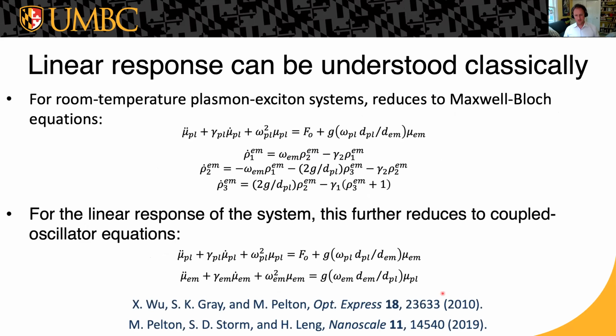And if you're interested only in the linear response of these systems, relatively weak excitation intensity, where the system stays in its ground state, then this reduces further to a fully classical pair of coupled harmonic oscillators, where each oscillator represents the dipole moment of, say, the plasmon and the dipole moment of the exciton. They're coupled together through the near field of the plasmon. And this simple pair of classical coupled harmonic oscillators reproduces quantitatively the linear spectra that you have in these systems.